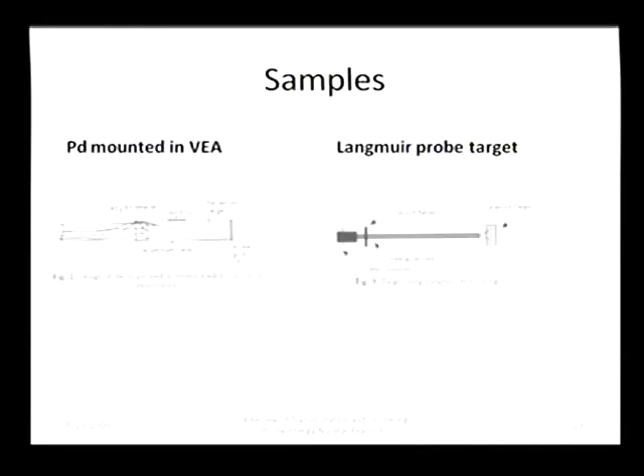The palladium samples were put into two structures. One was a classical ion analyzer, or ion energy analyzer. In essence, it had an aluminum case, and then basically it had a grid that allowed the ions through, and a target, which was the palladium target. We were able to adjust the voltage on the grid to adjust ions being able to reach the palladium target.